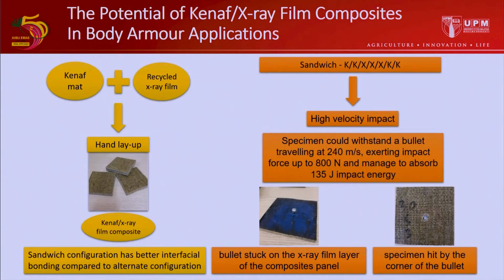It was also discovered that bullets generally entered the kenaf fiber layers in front of the specimen and were bounced back or trapped in the X-ray film layer. These results suggested that X-ray films are the primary cause of the composite material's impact resistance, while fibers such as kenaf operated as the ceramic front of the multi-layered armor system.